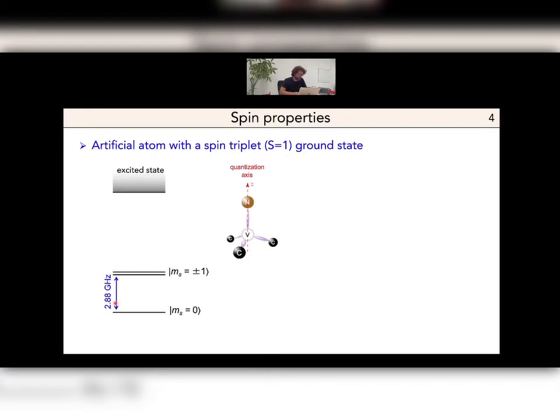There are two key properties of the NV defect, and I will not go through the details, I'll just give you the results. The first one is that if you just shine a laser onto the NV defect, there is an efficient polarization of the spin in ms equals 0. Starting from a thermal equilibrium with equal population in all three spin sublevels, just by shining a laser, it's possible to have polarization in ms equals 0.